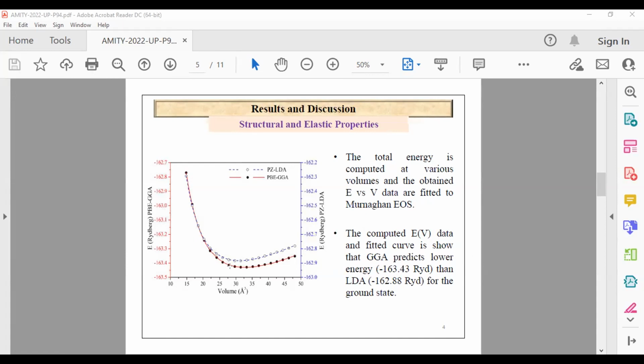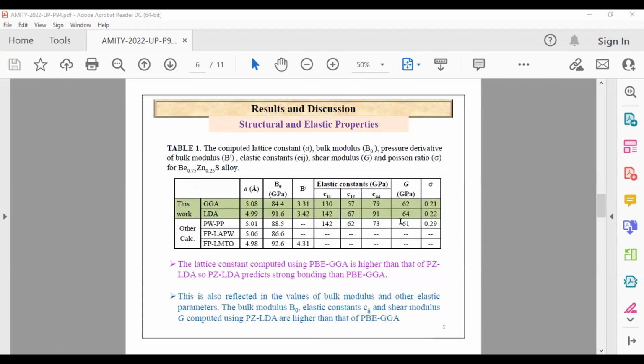The computed energy versus volume data are again fitted to the Murnaghan equation of state, and by this we can calculate the total energy, bulk modulus, etc., and various other properties. The computed properties are shown in this table, and we can find that the lattice constant obtained by GGA is higher than LDA, and consequently the bulk modulus and elastic constants calculated using LDA are higher than GGA. This is the trend of GGA calculations that they overestimate the lattice constant.